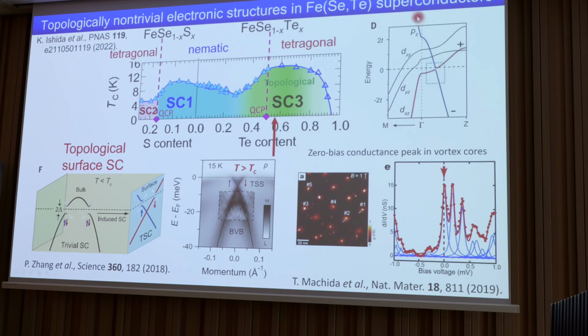What happens is that this chalcogen P band is going down from the top towards the Fermi level, and then the electronic structure is becoming topologically non-trivial only in this SC3 region, in this total electronic phase order.